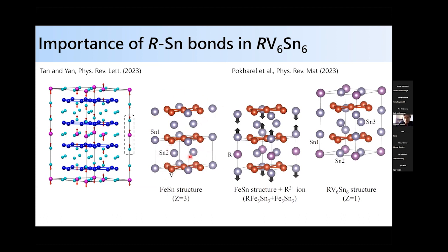And then if I think about this tin-2 site, this forms a honeycomb network in this plane. And in the centers of those honeycomb sites, you could put the rare earth ion when you start to make a 1,6,6 compound. And that'll displace the tin atoms above and below out of the kagome network where the vanadium ions sit. Since you've created this squeeze space and the layer immediately above or below it, you end up with a bilayer structure, because you can only put one layer of rare earth ion for every 2 vanadium planes. And so what you end up with is this 1,6,6 structure.